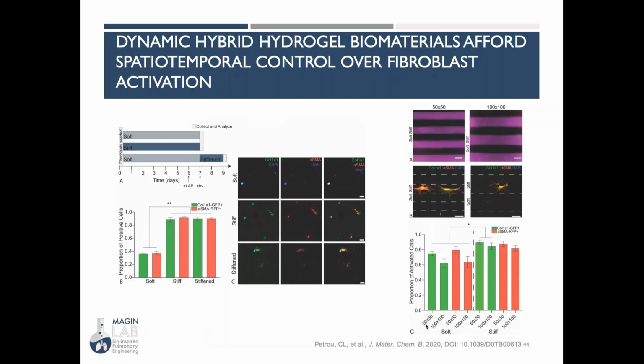It's been really exciting to work on these types of materials because we have both temporal control. We can stiffen over time and achieve activation of these dual transgenic reporter mouse cells. So we see expression of collagen 1 and alpha smooth muscle actin increase in our stiff and stiffened microenvironments. And we can also use light to control where we stiffen. So we have spatial control over stiffening that will allow us to start to recapitulate the pulmonary fibrosis microenvironment, where the changes in lung stiffness are not homogeneous, they're heterogeneous, and they change over time.